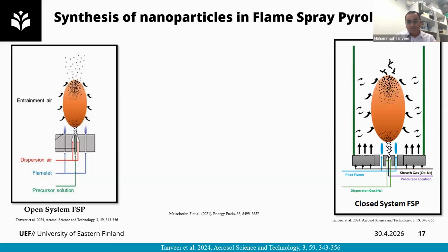The next setup that we have used here for the carbon dots is a closed system. Here we have introduced a quartz tube that can entrap the flame. When we ignite our precursor, we have very limited oxygen from the surroundings, because the flame is entrapped inside the quartz tube. Due to this oxygen deficient environment, we have an opportunity to control the combustion conditions. This enables us to produce and tune the carbon nanostructures, carbon dots here. Also, due to this quartz tube, the flame is quite hot compared to the open system, so we can induce in situ graphitization of our material. So it has numerous advantages.